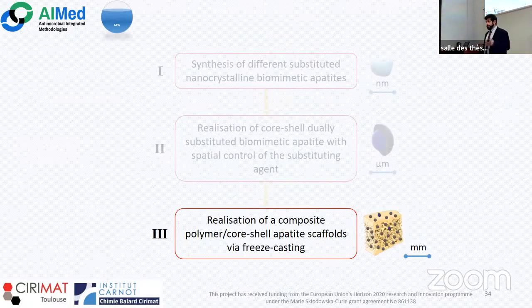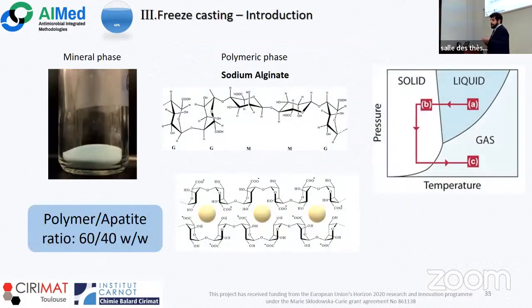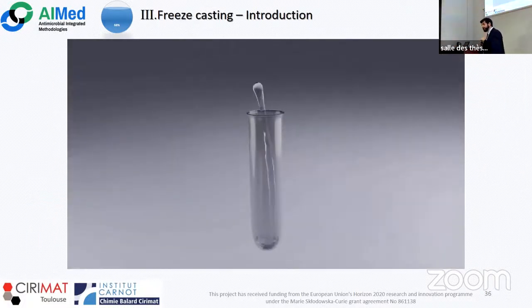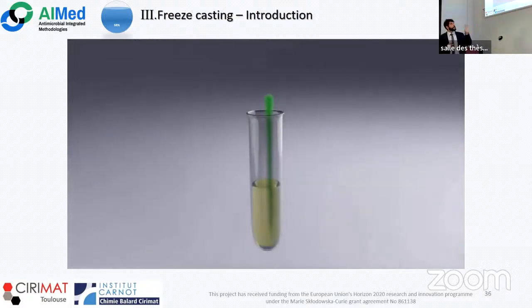Now, we want to use them in a real three-dimensional material. So we decided to use the freeze casting technique and to realize a composite scaffold between the mineral phase, that are the particles that we just discussed, and sodium alginate, that is a polymer widely used for biomedical applications. And furthermore, it is soluble in water. And being soluble in water, we can control better, and we have a wide knowledge of the phase diagram of this solvent.